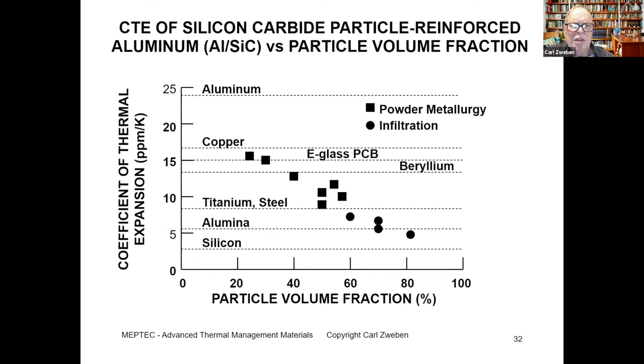So this chart shows the coefficient of thermal expansion of AlSiC, which is aluminum reinforced with silicon carbide particles, as a function of particle volume fraction. And we have two types of processes, powder metallurgy, that are these square points. With the powder metallurgy process, you can go up to a particle volume fraction of about 55%. But with the development of infiltration processes, you can go up to over 80% particle volume fraction. And the CTE gets down pretty close to that of silicon.